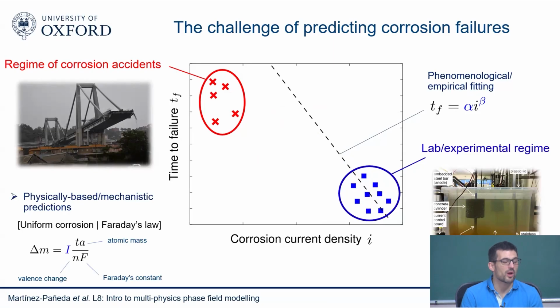This is when we have uniform corrosion, where we use Faraday's law. So here, this is Faraday's law. It tells you the change in mass as a function of the current, versus quantities that have a clear physical meaning: atomic mass, valence charge, Faraday's constant, and time. So this is good. Now there's no alpha, beta, there's no fitting to experiments. We have a model that is physically based, that relies on material properties that we know, that we even know before we run an experiment. So this is very good, and this has proven to work very well. So uniform corrosion is something that we understand.